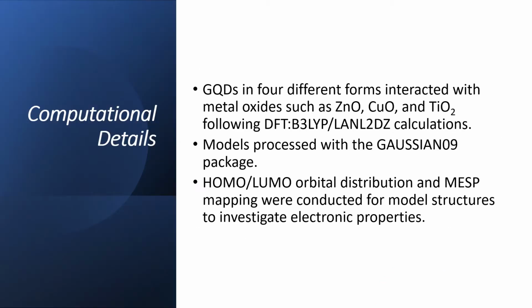So, our computational details: graphene quantum dots in 4 different forms interacted with metal oxides such as zinc oxide, copper oxide, and titanium dioxide, following density functional theory at B3LYP/LANL2DZ calculations. Models were processed using Gaussian 09 software. HOMO-LUMO orbital distribution and molecular electrostatic mapping were conducted for model structures to investigate electronic properties.